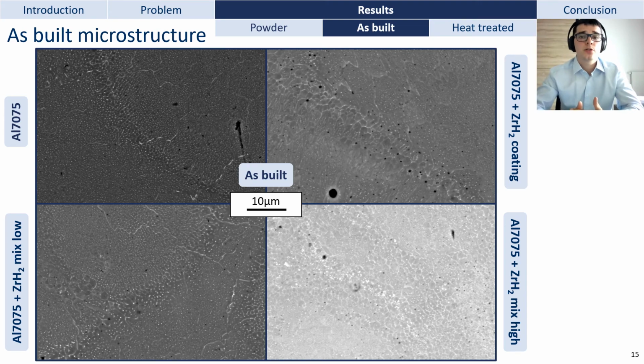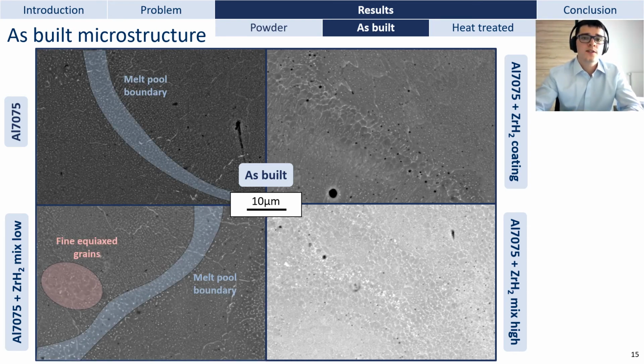Now that the optical microstructures have been analyzed, let's look at the SEM pictures to describe the microstructure more closely. First of all, we can see that the microstructure of the aluminum 7075 and of the mix with low zirconium content are quite alike. A finer microstructure delimits the melt pool boundaries, and some continuous networks of precipitates delimit grains inside the melt pools. We can also notice a small equiaxed grain region for the low zirconium content mix.